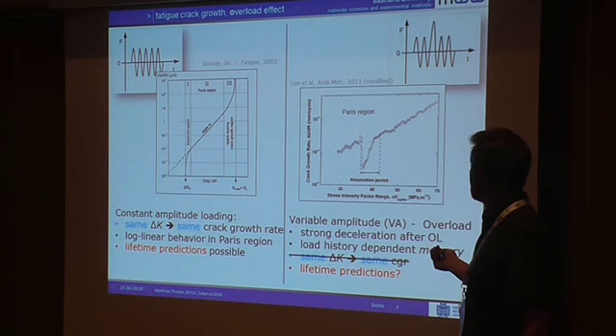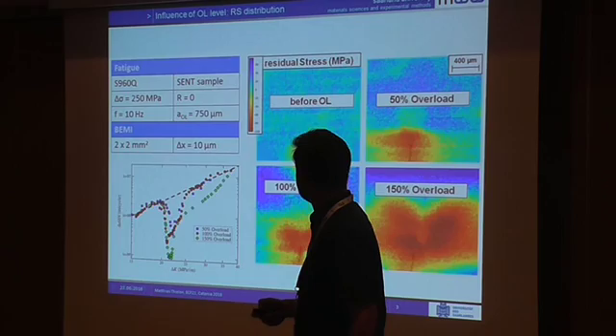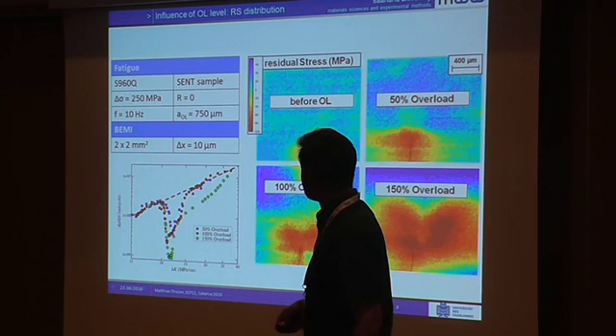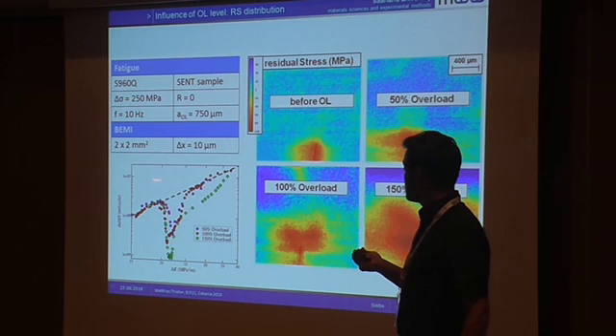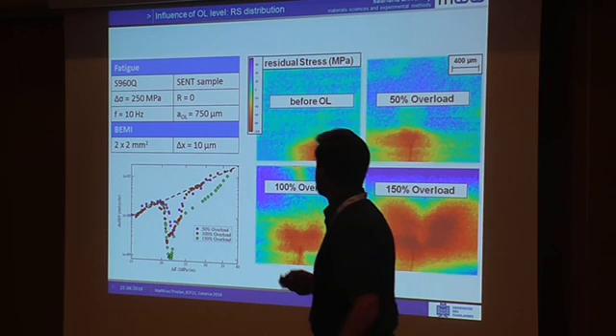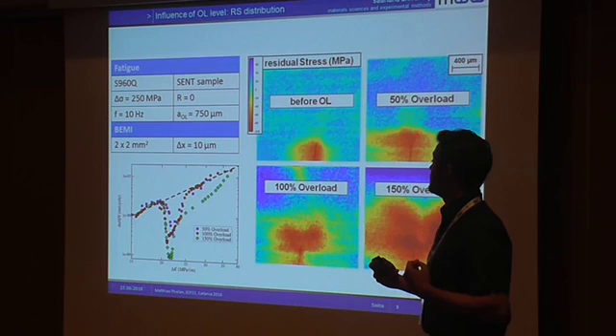And the similarity principle — the same data leading to the same fatigue response — obviously does not hold anymore. This raises the question about lifetime predictions. The nice thing about the overload effect is that when you increase the overload, the crack becomes slower, which is somewhat consistent. This mechanism is mainly driven by residual stress, so it is quite interesting to have a look at the residual stress. And that's what we did.